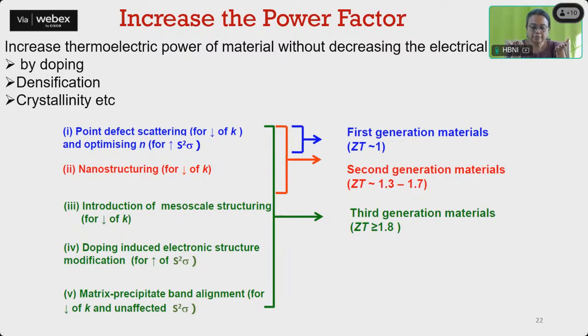The other things which are done to increase the power factor are point defects. We are introducing point defects to scatter phonons and decrease the thermal conductivity, and we are optimizing the majority carrier concentration so that the power factor increases. So this was done initially in the first generation thermoelectric materials to achieve a ZT of around 1.